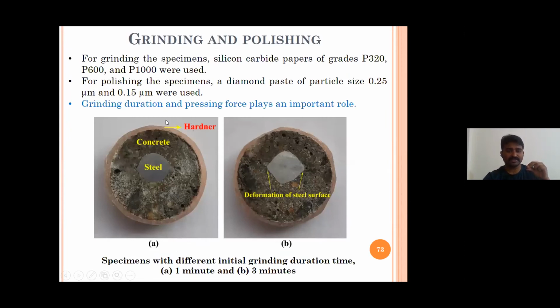The next step is grinding and polishing. Once the epoxy is done, I have to grind and polish it. For grinding, we have used 3 silicon carbide papers: P320, P600, and P1000. These are just like sand papers, and on those we have to grind it. I have used an advanced polishing machine where we can even control the pressure that you apply. Then for polishing the specimens, we have used diamond particle paste, that is 0.25 micrometer and 0.15 micrometers.